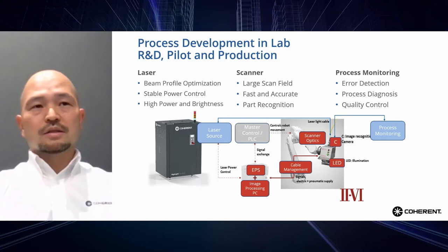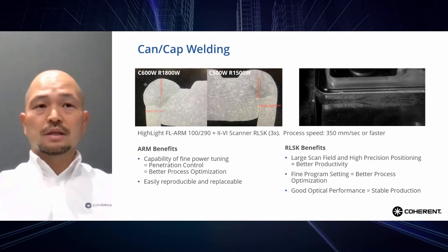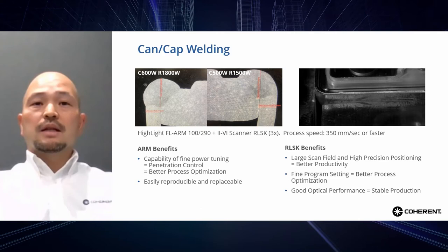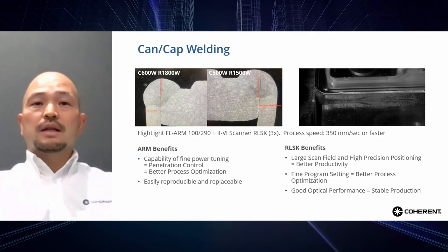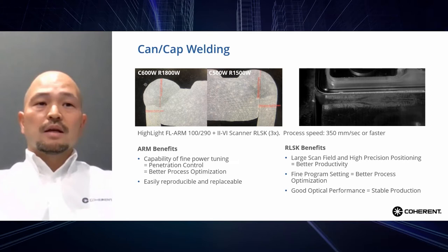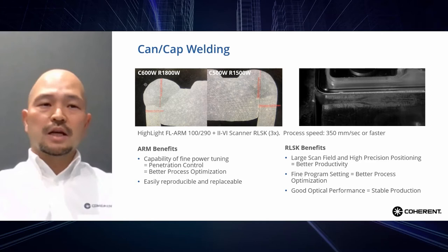Can-cap welding is one of our successful applications in Japan and also globally. What's important for a good weld is reproducible hermetic sealing for mass production — wide weld bead and stable penetration at high speed. The laser can control the penetration depth and the bead width independently, giving design freedom compared to other lasers. For deeper, shallower, wider, or narrower geometry, hardware changes were required to adjust weld geometry for conventional lasers, but not for the ARM laser.